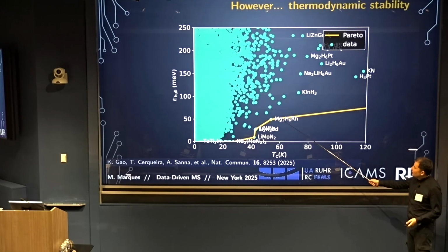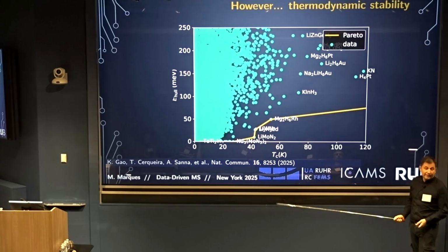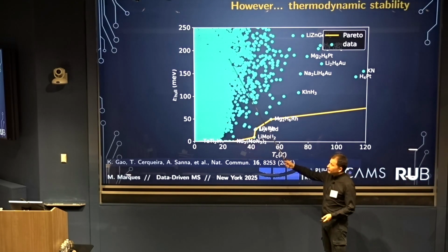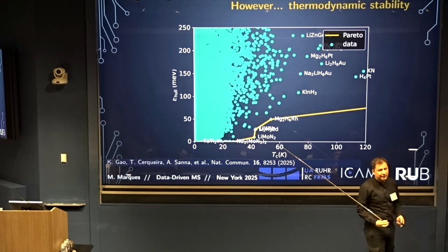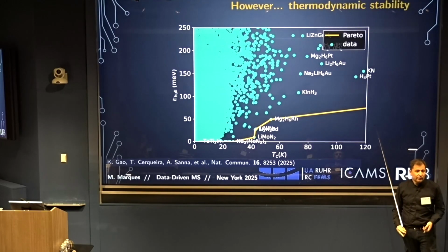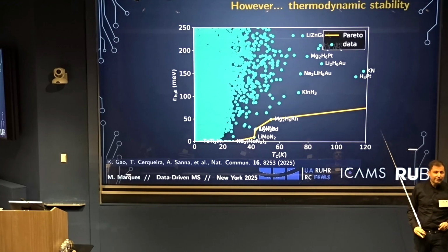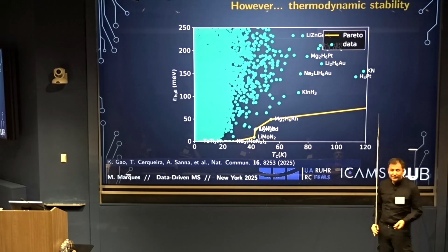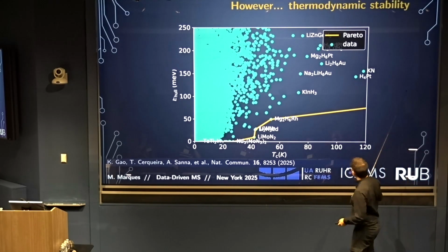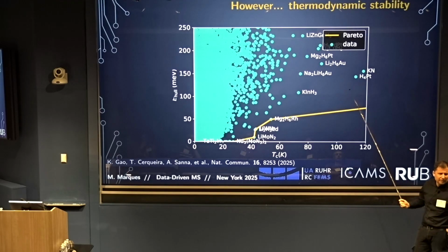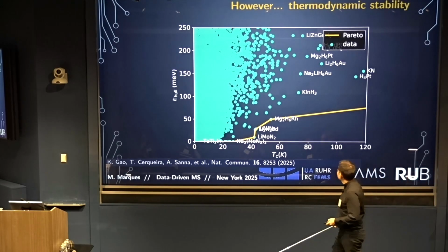And then you see the price you have to pay to get a hydride: between 50 and 200 meV per atom. That's the price you pay to make a metallic hydride. The hydride closest to the convex hull is a palladium hydride, that actually exists. I don't remember what is here, I'm sorry, I didn't look. I think it's something with thorium, but it's not a problem.